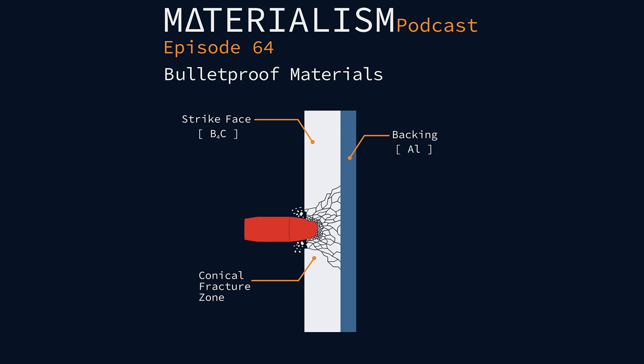And there's a couple configurations that you'll see with the ceramic armors. The first consists of a thin ceramic tile mounted to a ductile metal or fabric behind it. This provides a much lighter configuration, and you have a couple of different effects that create some predictability in terms of the failure. When a projectile makes contact, you get high amplitude compressive stress pulses produced in the ceramic, and these will travel through the material. But the stress impedance between the backing material, which is a different material than the ceramic, causes those stress waves to reflect. And in the act of reflection, they transfer from compressive to tensile stresses.